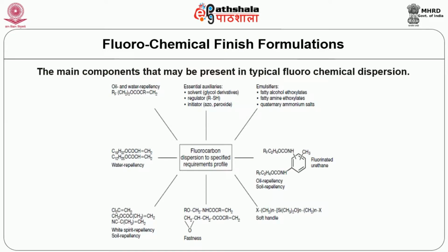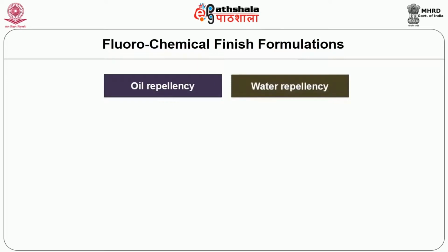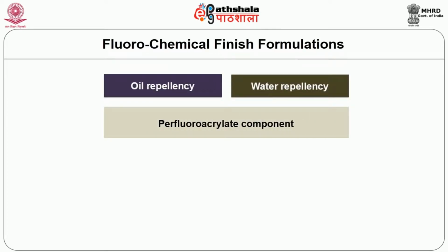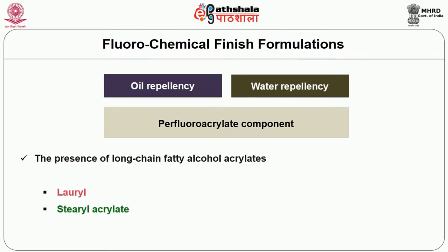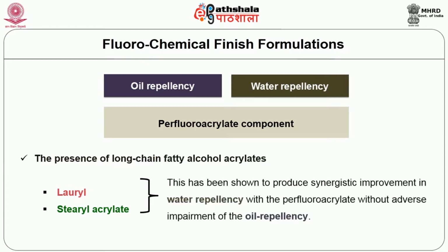The main components that may be present in typical fluorochemical dispersions are here. Oil repellency and water repellency depend crucially upon the perfluoroacrylate compound, but the presence of long chain fatty alcohol acrylates such as lauryl and stearyl acrylate has been shown to produce synergistic improvement in water repellency with the perfluoroacrylate without adverse impairment of the oil repellency.